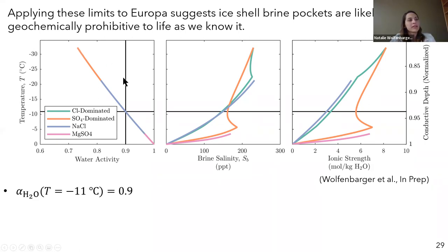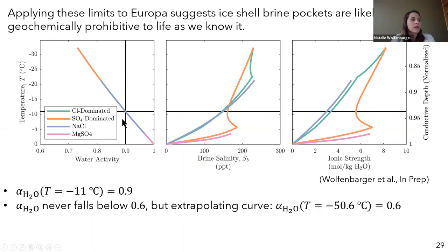So importantly, we have a temperature of minus 11 that characterizes the transition to the extremophile regime. And it never really falls below this lower limit of 0.6. If we were to extrapolate this curve, it would suggest that where brine could be stable down to minus 51 C, you might run into this problem where water activity is governing the habitability of your brine system.